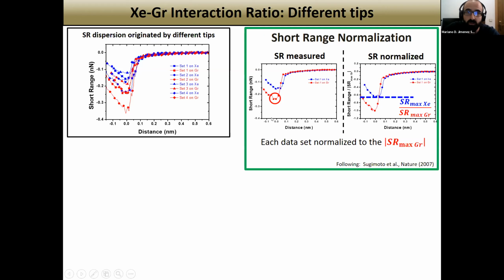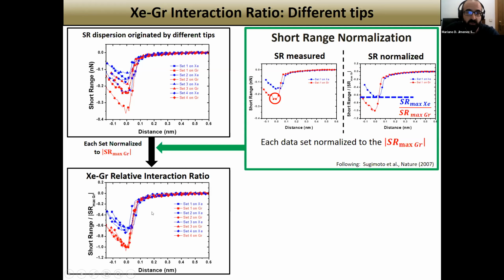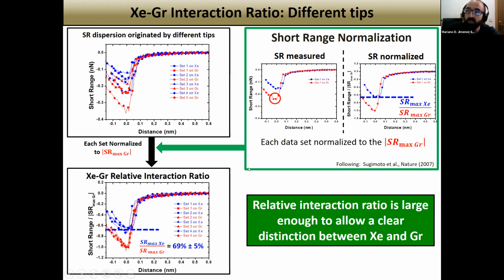So if we take this normalization and apply it to all this data, what we observe is that the dispersion has been dramatically reduced, and from this plot we can evaluate the relative interaction ratio, which is 69%. And what's more, we can also observe that the relative interaction ratio is large enough to allow a clear distinction between xenon and graphene areas, independently of the tip. I mean, we haven't observed any case in which the force measured on xenon is close enough to the force measured on graphene to give rise to a confusion.